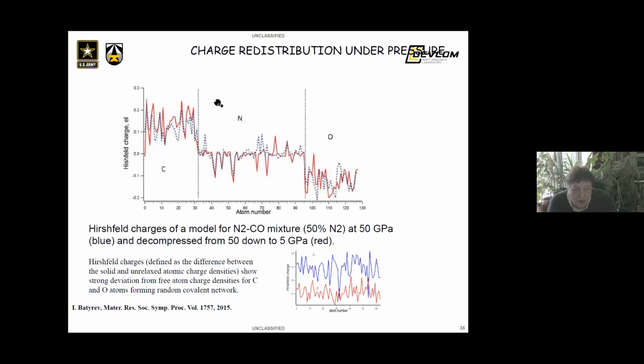This slide shows modification of Hirschfeld charges under pressure. Let me remind that the Hirschfeld charge is defined as the difference between the solid and unrelaxed atomic charge density. One may see from the figure that there is an increase in minimum charge peaks for nitrogen upon decompression from 50 GPa to 5 GPa. And these negative peaks correspond to the ends of the chains. At the bottom of the page, there is the same kind of picture for polyCO at 13 GPa during partial polymerization. So you also see these peaks, and they correspond to the ends of the chains and to the atoms which will be disconnected first upon decompression.